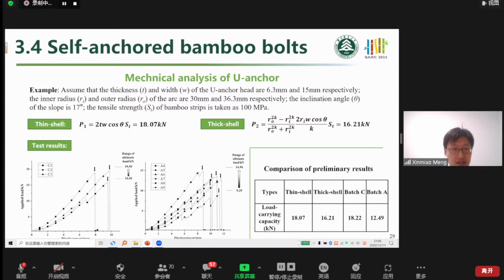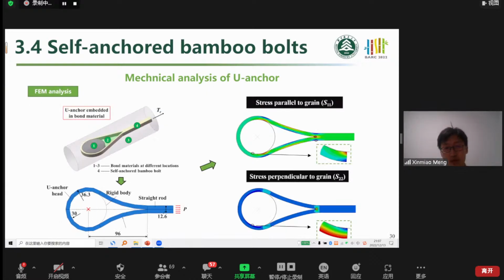Then we combined these two methods together, and here are the theoretical results. This is the experimental results. We found the results showed large deviation. So we think we need lots of tests to evaluate the accuracy of these two models. And we also conducted a finite element analysis to verify the theoretical model. It proved the effectiveness of the thick shell model.